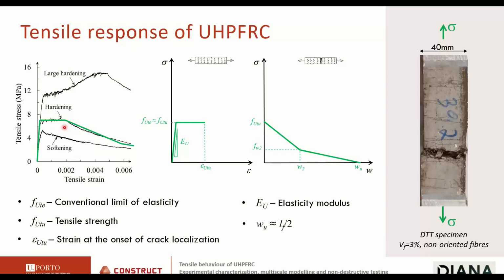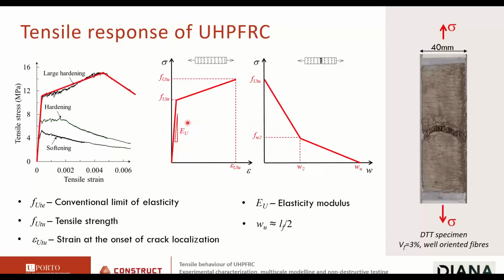So I forgot to mention, we just need three parameters to describe this curve. It's the ultimate strain at the onset of crack localization, the tensile strength, and the Young modulus of the composite. In this case, this value is different from this one here. So in this case, we have to define a conventional limit of elasticity for our material.